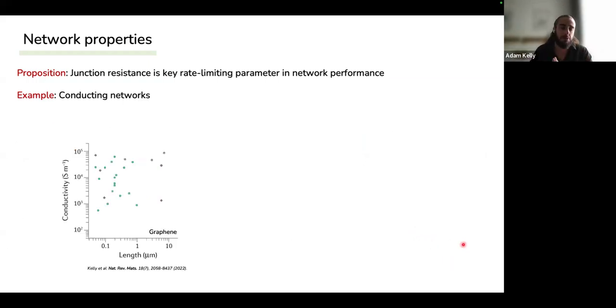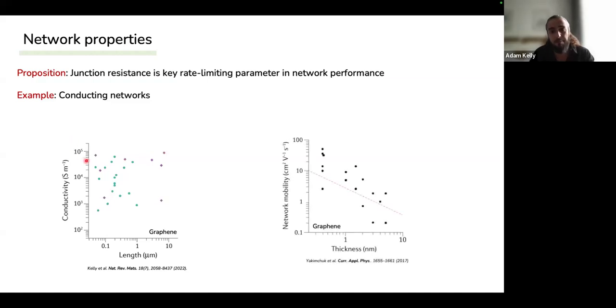So that's semiconducting networks. Does this also transfer over to conducting networks? Well, we took graphene. I took as many of the papers that I could find that reported conductivity and length statistics. And what we found is that there's basically no correlation here, as far as I can tell, on this graph. So you can have long nanosheets with high conductivity in your network, and you can have small nanosheets. So this means that length is probably not the relevant variable.